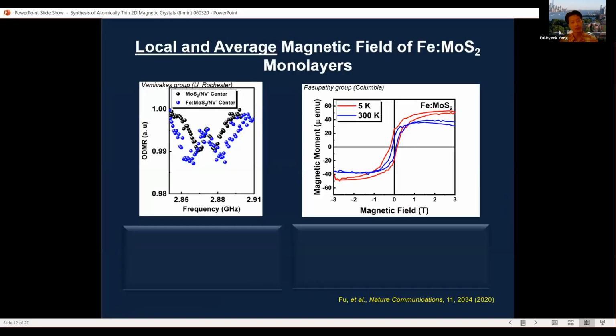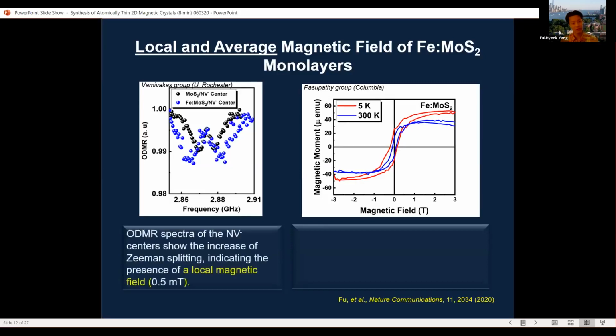It is also important to show and confirm the magnetic field from the material locally as well as globally. Globally means the average magnetic field. Local is important because we have to confirm that this magnetism comes from these doped atoms, right? For the local magnetic field measurement, we used optically detected magnetic resonance spectra of nitrogen vacancy centers, which are basically nanodiamonds with defects spun onto the sample. You measure this increase of Zeeman splitting, as you can see from these blue dots, and that indicates the presence of a local magnetic field.